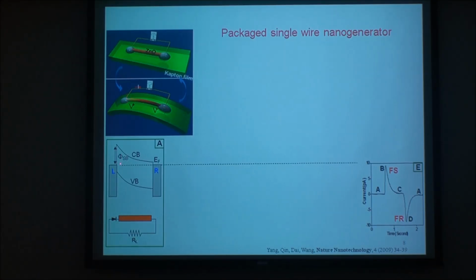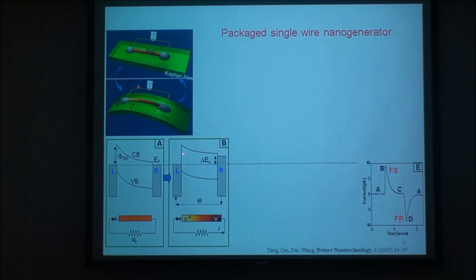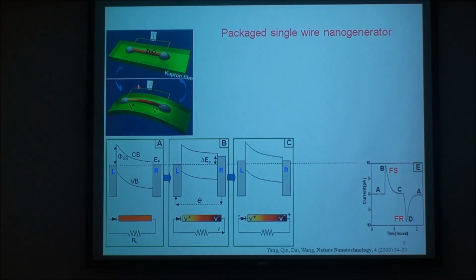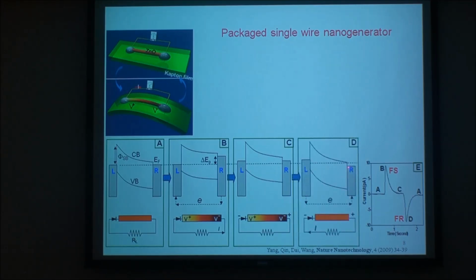But here is a Schottky barrier, and the Schottky barrier will hold the electron around here. So the electron flows to balance the Fermi level on the two sides. You see the first output peak, and this is the first signal, then it reaches a new equilibrium. And once this is released, the electron flows back, and because of the Fermi level difference, the disappearance of the piezo potential gives you another peak.